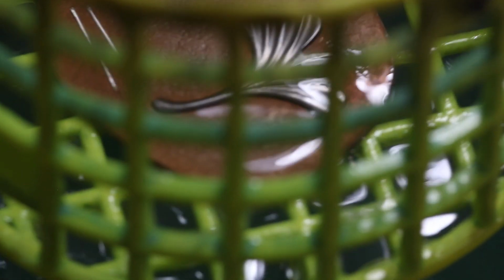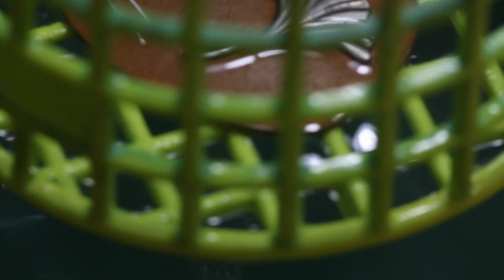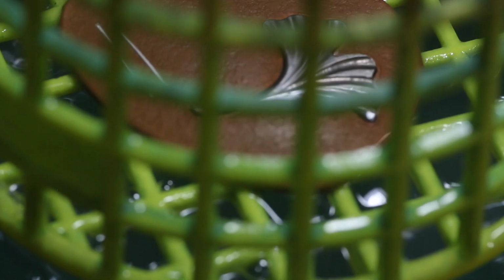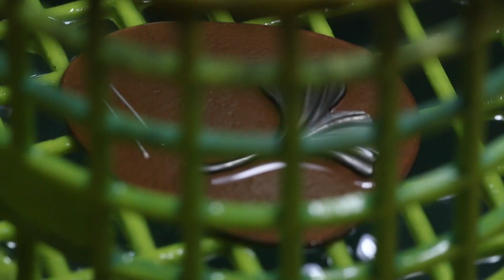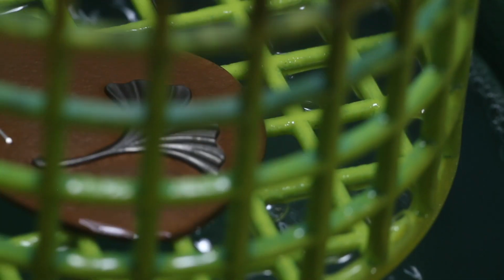Now this hasn't taken an awfully long time, but the colour is now developing as it needs to. And we could cut back to this in 20 minutes, and I'll show you where we're at. You see it, that's a perfectly reasonable patina. I'm leaving it wet, so I don't want it to dry out. As I said, that could cause problems.